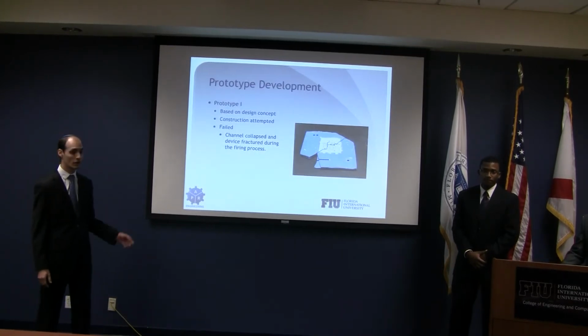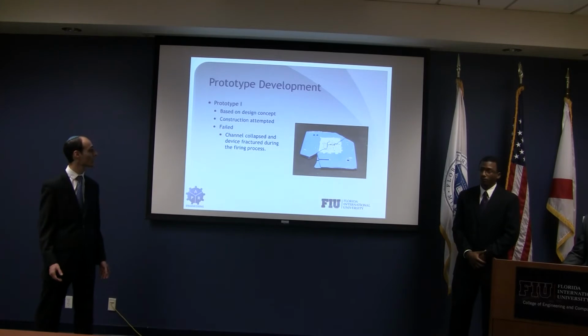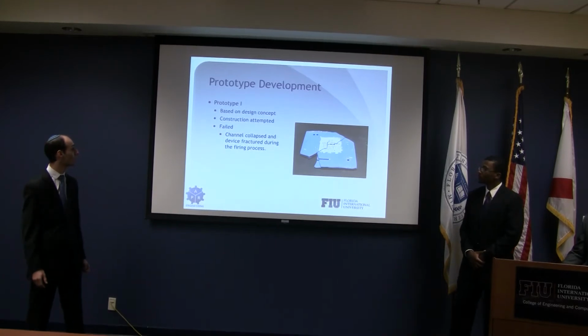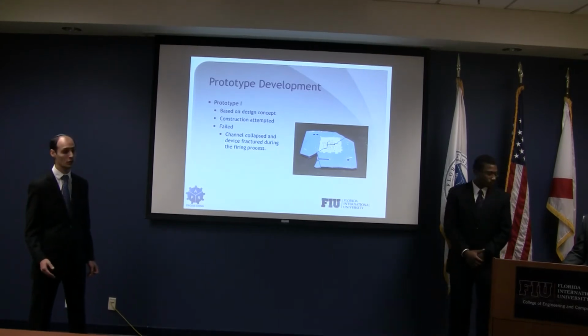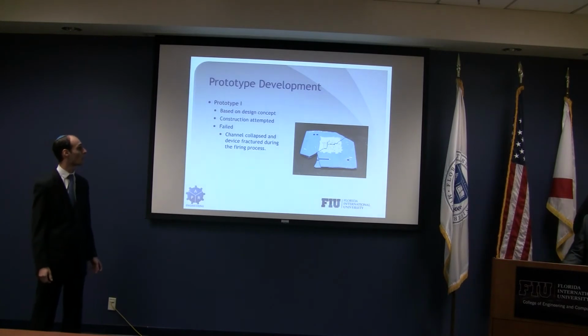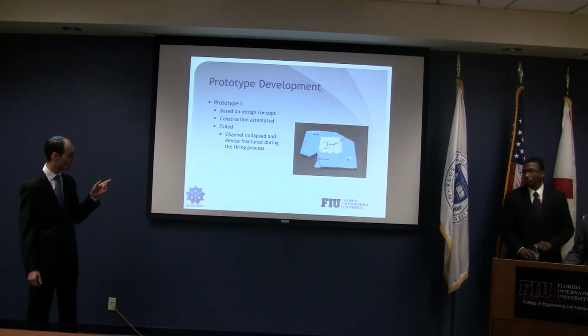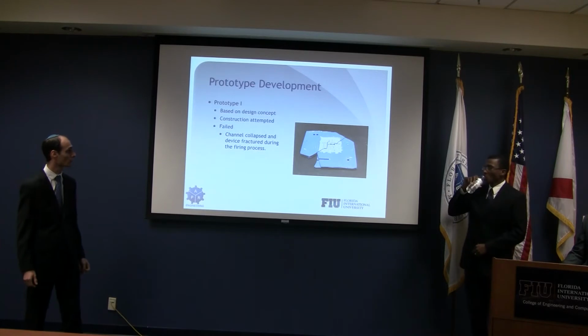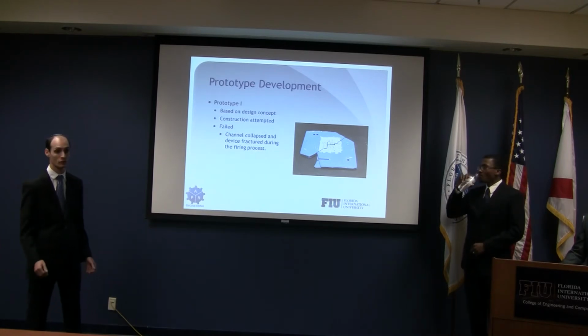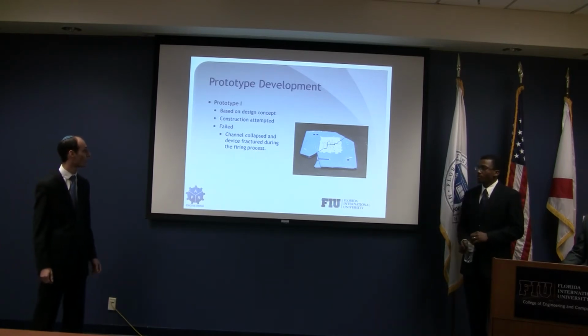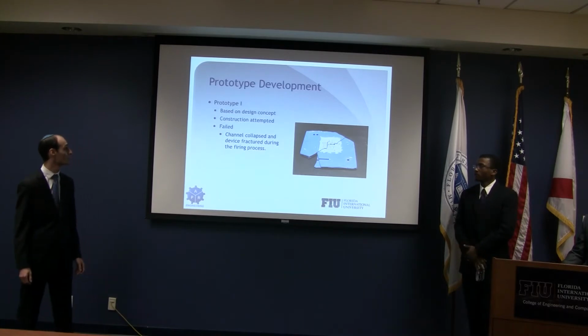So when we manufactured this one, it worked perfectly well, except for in the firing. During the firing, we had a fracture and collapsed channel. All the cracks that you see here, the only ones that actually happened during firing were the ones in the center. The rest of them happened during post-processing, trying to figure out what happened. So we went on to a second prototype.